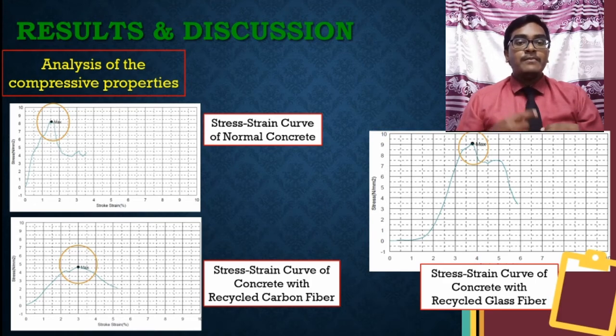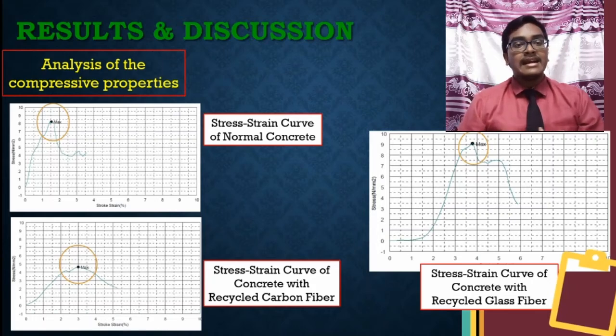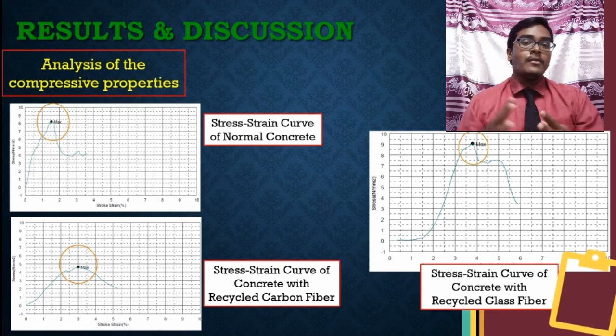The favorable improvement was about 53.78% compared to the normal concrete. This is because the silica in recycled glass fiber has very strong bonding with the silicon dioxide present in the concrete. The lowest Young's modulus was detected from the sample of concrete with recycled carbon fiber, which is 3.80 megapascal. There is almost a 15.56% reduction compared to the normal concrete.